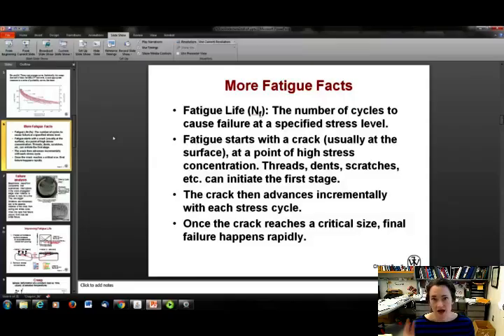Fatigue, when it starts, happens in 3 stages. It usually starts off with a crack or a scratch or something like that. So you have a defect in your surface. It could be the threading on your bolt, it could be a dent in your surface, a scratch, a rusted spot, whatever. And then at that defect, a crack will form, okay? And this usually happens at the surface.